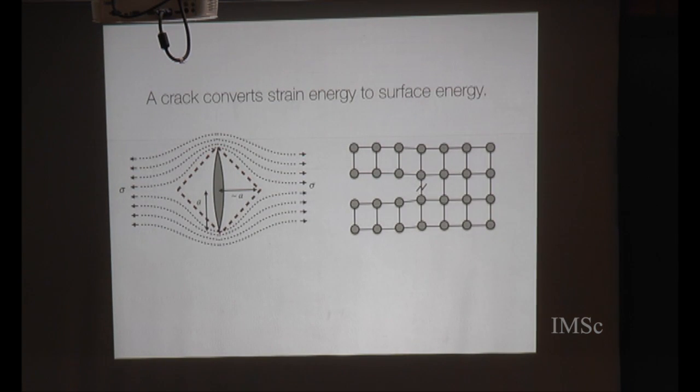Basic fracture mechanics, not necessarily necessary for this audience, but some of the students might still benefit. If you have a crack, the stress lines get deflected around it. There's a stress singularity at the crack tips. This clears out something which geometrically has an area about the size of the crack squared, which then is relatively stress-free. So there's focusing on the crack tips, and there's a stress release.